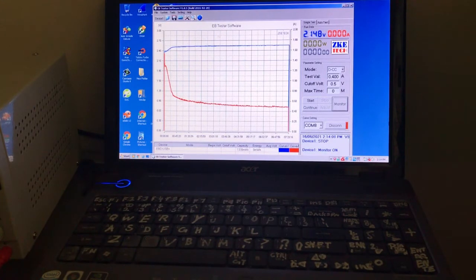59 charges on the cell, 7.5 hour charge. Going to try a 400 milliamp load test today, just to stress the cell out a bit. Starting test now. Okay, holding 400 milliamps okay. It may get about an hour, or just over an hour at this rate. Looks like it's coping okay. It's 1.8, dropping fast there.